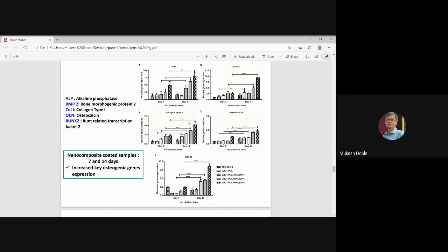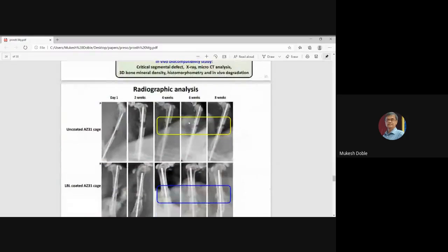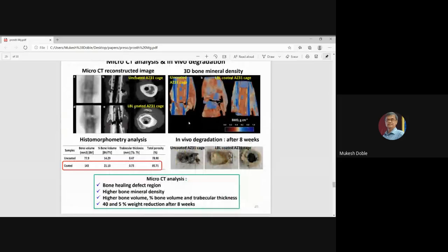So the in vivo studies are extremely encouraging with respect to the formation of the bones, especially the bone percentage, volume, the porosity of the bone, the growth of the bone, and the healing process of the animal, as well as the biodegradation of the material, which was much lower when compared to that of the uncoated material, because we do not want the material to biodegrade much faster than the healing process of the bone defect. So as the bone defect is completely healed and the bone is totally grown, we want the material to get degraded, which may be taking place in about 1.5 to 2 years. So we want a material which degrades at that point of time rather than at an earlier time.